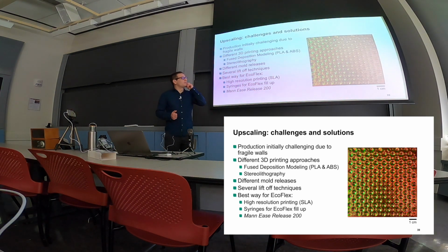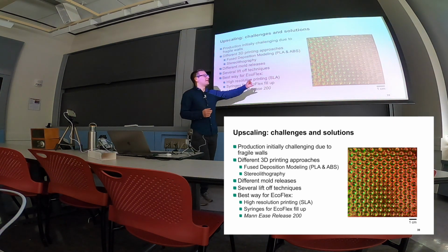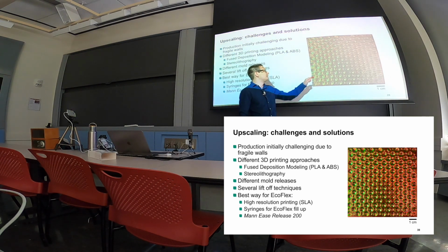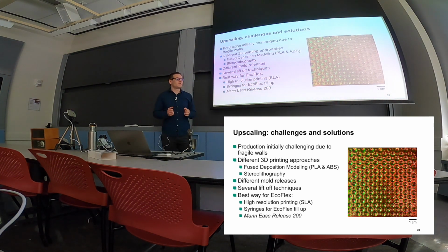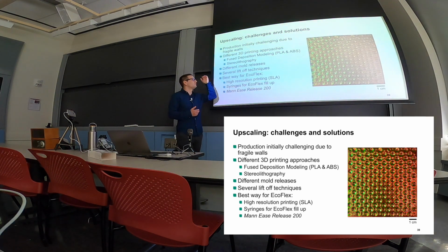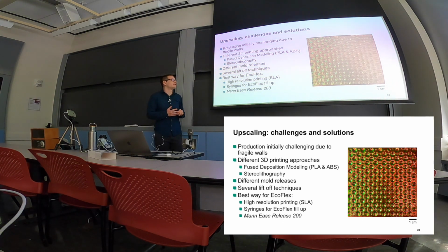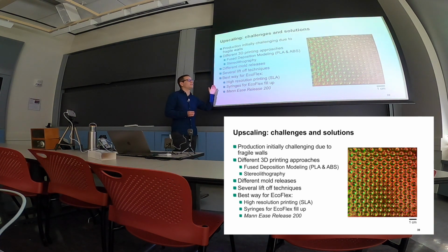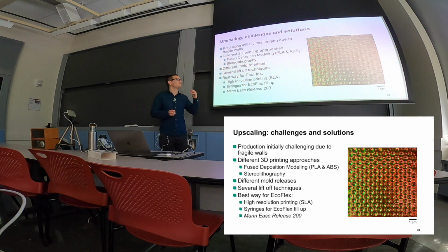But I wanted to just recapitulate the steps to get to such a huge system. As mentioned, the high aspect ratio and the extremely thin, sub-millimeter thick walls have been a huge problem when trying to remove the metamaterial out of the mold, because they usually tear when trying to do that. And so I played around with different 3D printing approaches, so I used fused deposition modeling or stereolithography and tried different materials. I also tried different mold releases and several lift-off techniques, and after some time figured out that, at least for Ecoflex, it is best to just use the highest printing resolution. So if it is financially possible, then always use stereolithography, because it has much flatter edges.